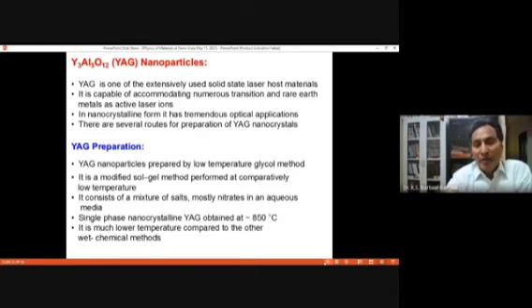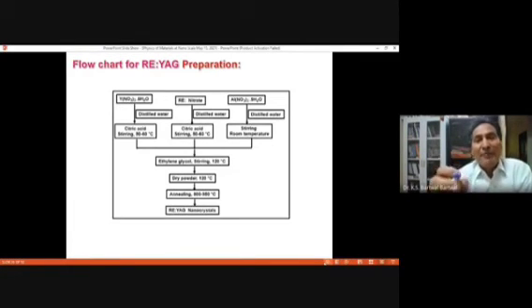This has been made in 30 to 50 nanometer size and at a very low temperature, only 850 degrees Celsius. The melting point of this material is around 2000 degrees Celsius. However, by using this technique, the glycol method, it has been made at a temperature of 850 degrees Celsius. So this is one of the beautiful techniques for making this type of material, particularly high melting point material, at very low temperature. Only 800 to 950 degrees Celsius, you can get these YAG nanoparticles using the nitrates or sometimes carbonates of that particular material, and using this glycol route you can get these nanoparticles.